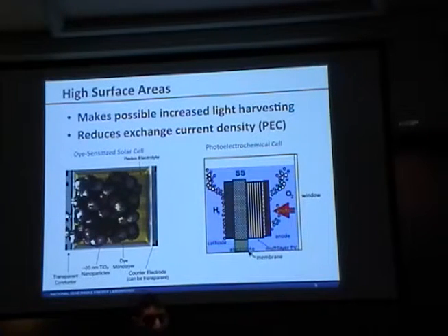Those charges have to react, and the faster they have to react, you have a greater exchange current density, and that puts lots of limitations on your catalyst at the surface. And so if you have a lower exchange current density, then your catalyst doesn't have to work quite as fast, and so that makes it a lot easier catalyst to design.